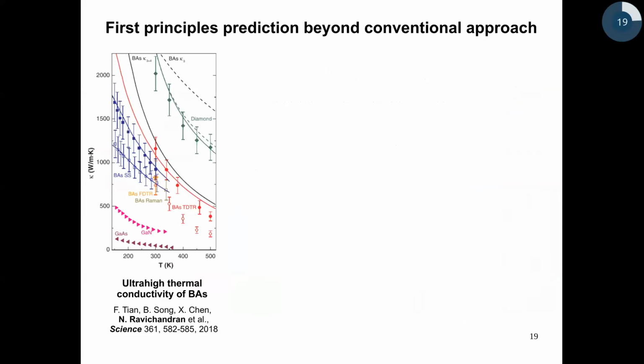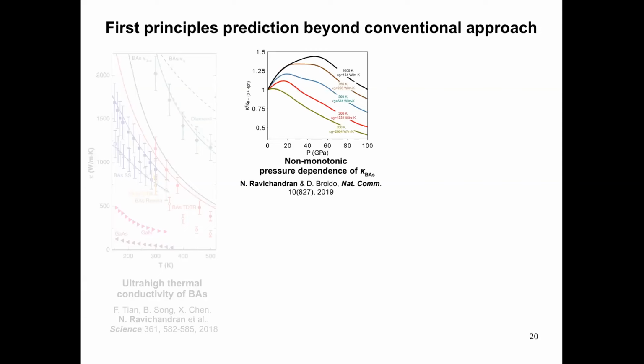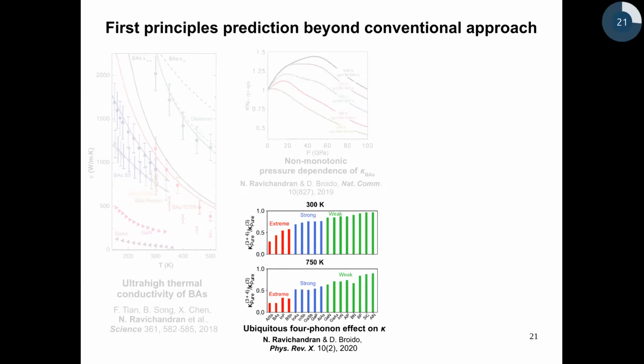Over the past 2 years, I have been developing a unified first principles framework, which includes higher order terms in the free energy and higher order interactions among phonons, to answer this precise question. Is conventional theory sufficient for all materials? In fact, using this unified first principles approach extended beyond the conventional theory, I have worked on several interesting problems, such as predicting the ultra-high thermal conductivity of this new material boron arsenide, and as a consequence, a very unique non-monotonic pressure dependence of its thermal conductivity, and also found that the effect of higher order phonon scattering, for